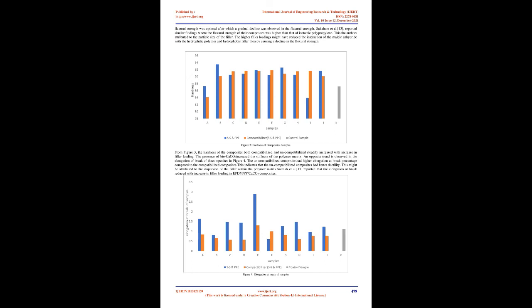Maleic anhydride addition to the composites increased the interaction between the polymer matrix and the particulate filler. A similar trend was observed by Mumu et al. 11. In this study, the tensile strength was significantly better than the control sample, pristine PP. Figure 2 shows the flexural strength of the pristine PP and its composites.